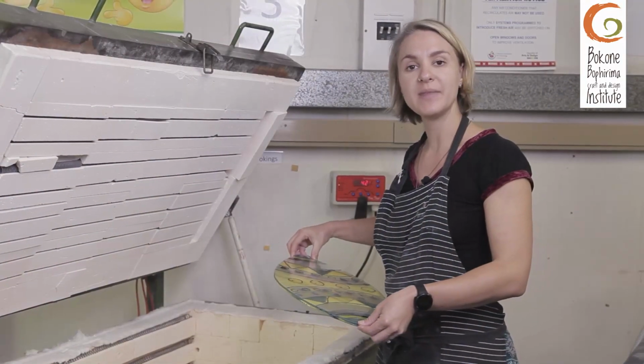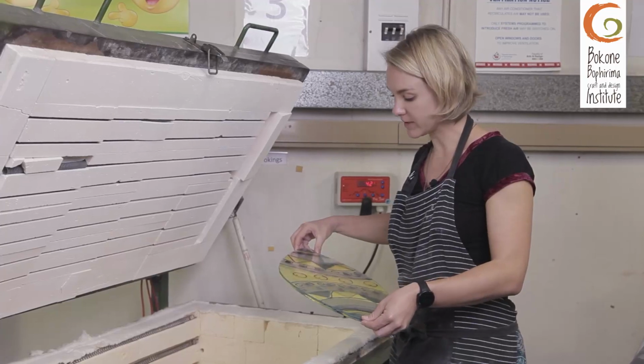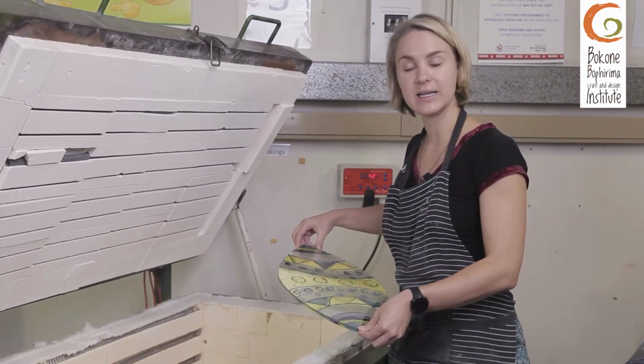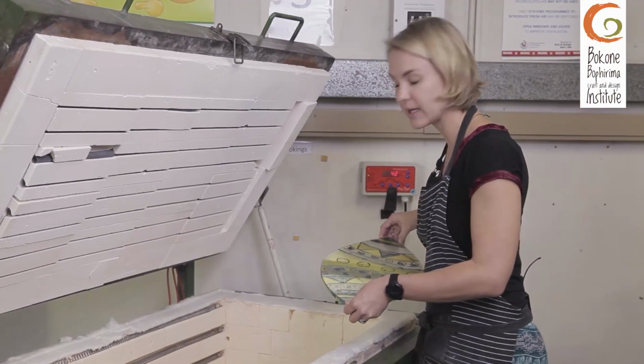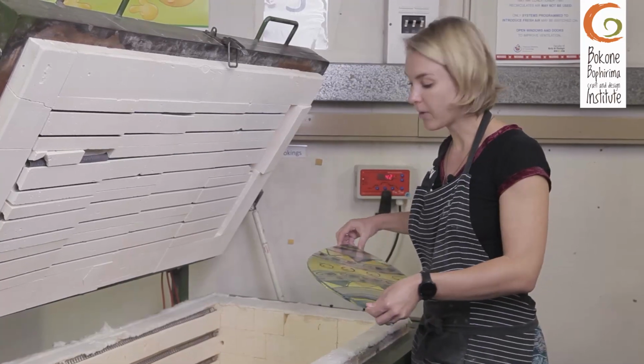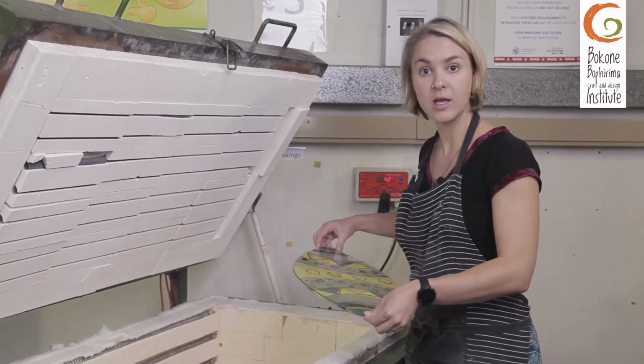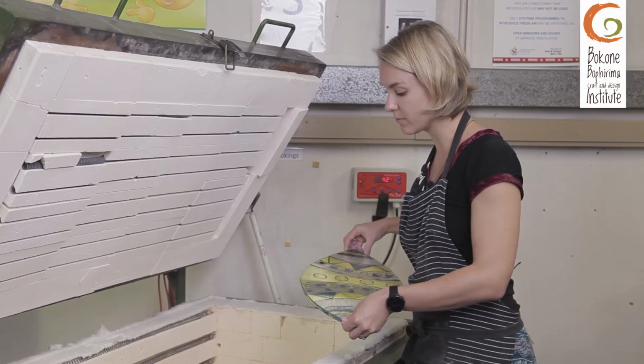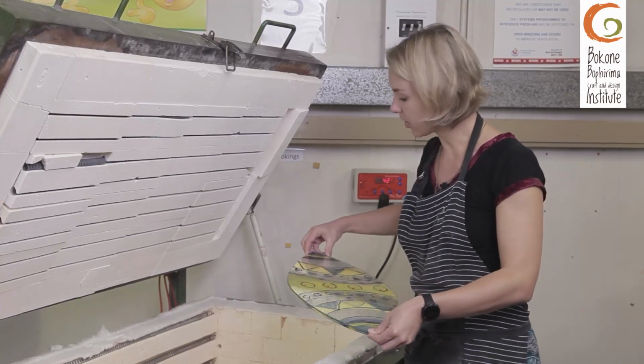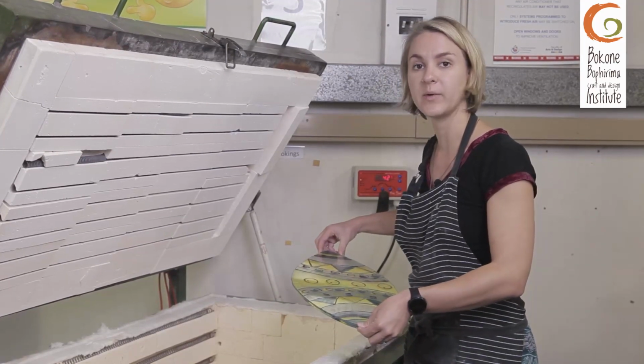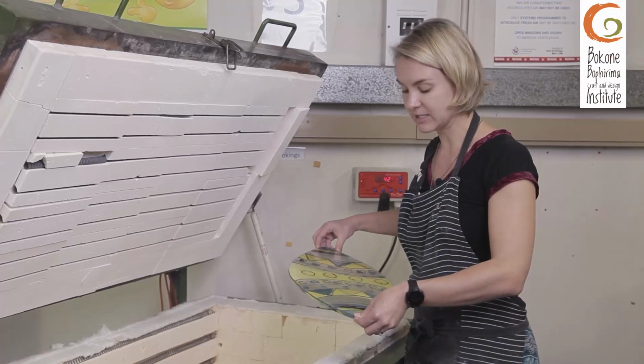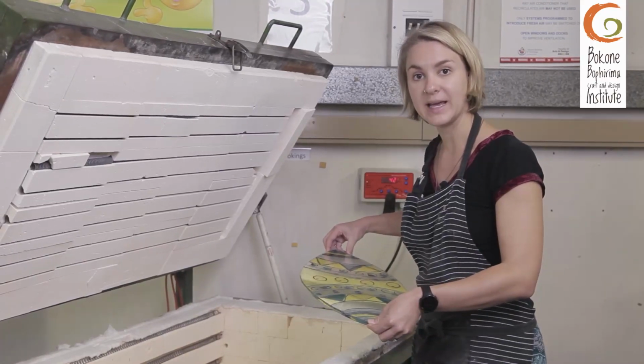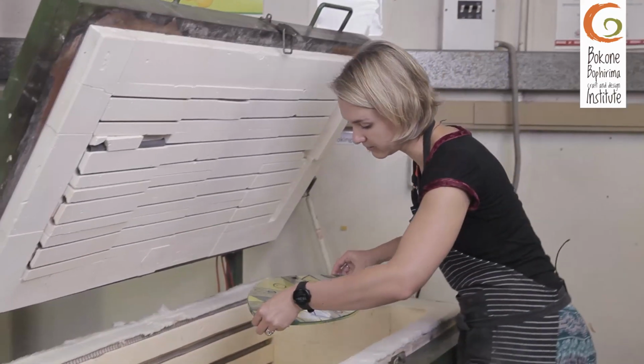Hi everyone, I'm now going to slump Lebo's platter piece, and my mold is in the kiln already, and it's got its plaster primer on, so the glass piece does not fuse to my mold. I'm holding the glass on its edges, and that is because I don't want to get any fingerprints. My glass has been cleaned, and I'm now going to place it inside my mold in the kiln.